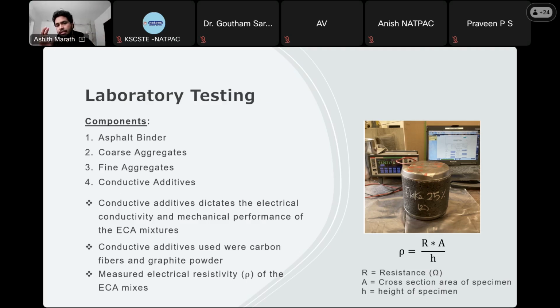If you look at this, you have two types of conductive additives: carbon fibers in the fibrous form and graphite in the powder form. The reason to use these two different kinds is to balance the mechanical and electrical performance of the mixtures. As you add more and more graphite into the mixture, it will start losing the cracking performance of the mixture. In order to compensate for that, we had to use certain doses of carbon fibers to reach a balance between the mechanical and the electrical performance of the mixture. In the lab, on the right side, you see how you measure the electrical conductivity of the asphalt mixtures using a multimeter. Once the resistance of the mix is determined, using the equations, we estimate the resistivity of the material.